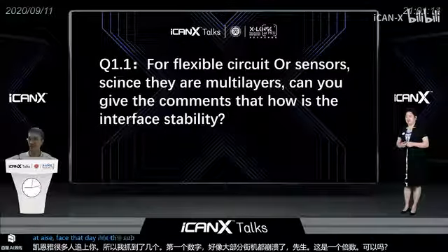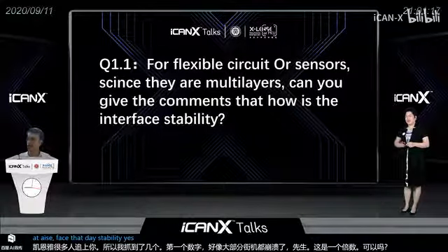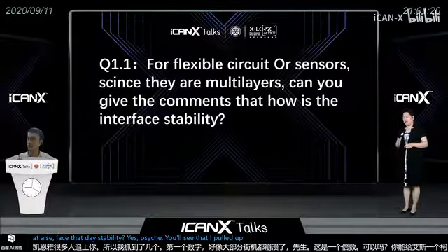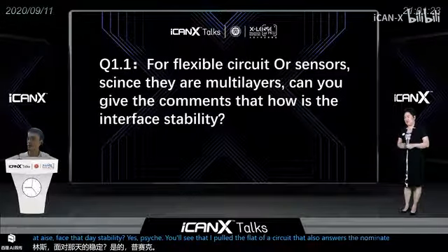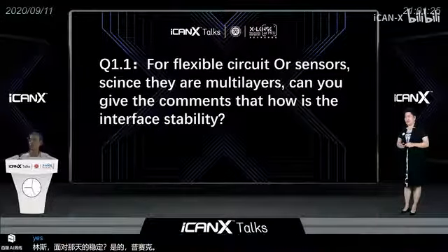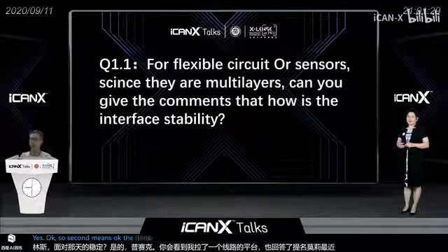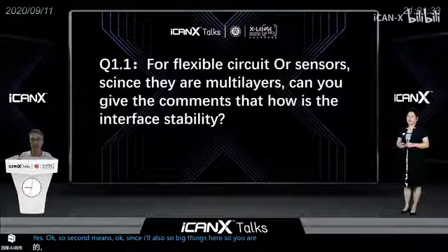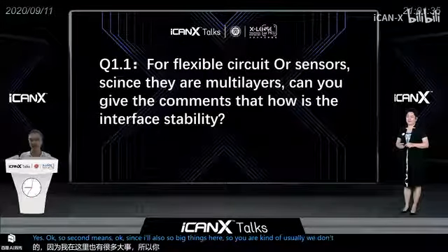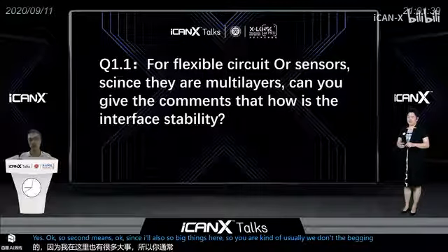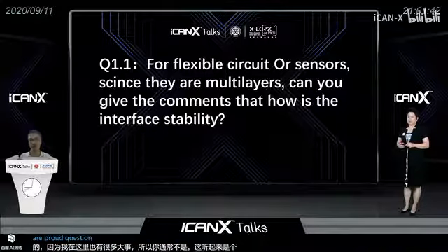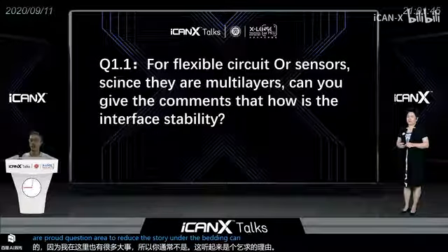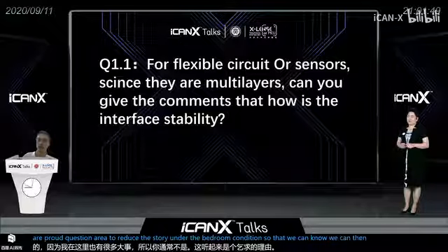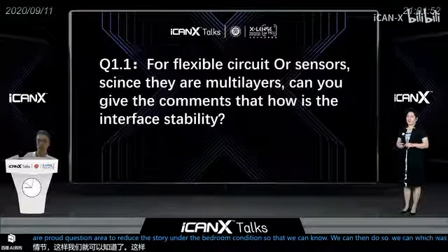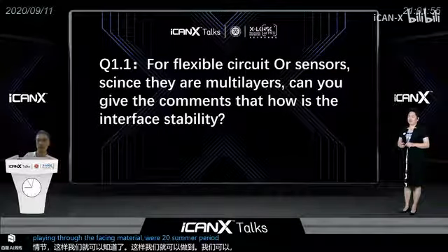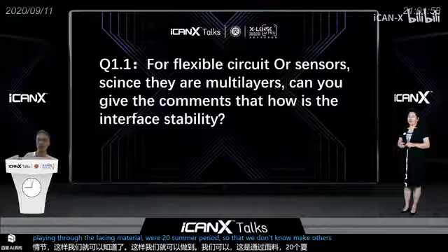Interface stability of the circuit? For the flexible circuit, all sensors are normally multi-layers. So circuit means the sensor also. Basically, we usually test 1,000 to 10,000 bending cycles. We always apply a passivation layer to reduce the strain under the bending condition, so that we can suppress the strain in the sensing material or transistor materials, and make a very stable flexible sensor and transistors.